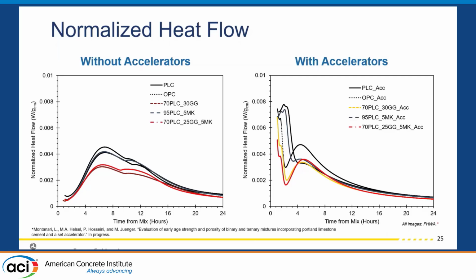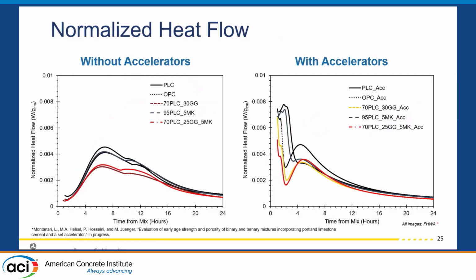So looking at our normalized heat flows, and this is, once again, back to those hydration kinetics, gotta love the basics. I apologize, on my screen, it has the dots, so you can actually differentiate all of the different lines, but on this screen here, you can't see them, so my apologies. The top one is actually OPC on the left, and then right below that is PLC. And you can see there's just a little bit higher of a peak with the OPC, but we're receiving the same general trends for all of those figures on the left.